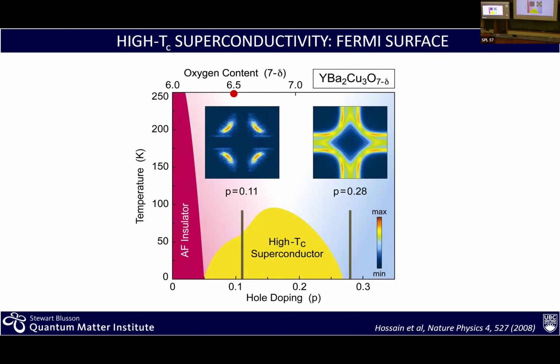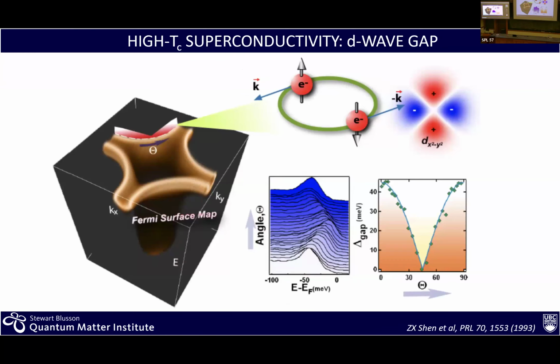And I'd like to note, as a specific aspect here, that you see the dome, which has this particular shape, has an anomaly here. And that anomaly has now been associated with a tendency of electrons, valence electrons, to charge order in these materials, which is what Eduardo has made a major breakthrough and contributed a major breakthrough to in his work as a student and postdoc, and even now. So basically, this is really the picture that we have for these materials. And that also relates to the superconducting gap.